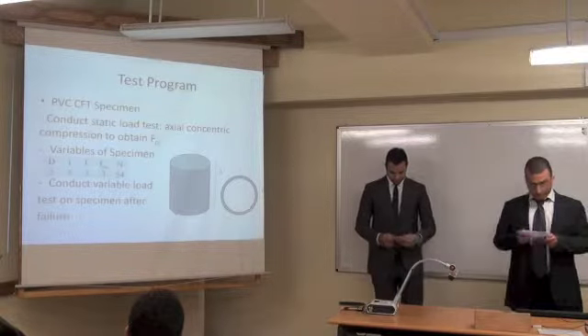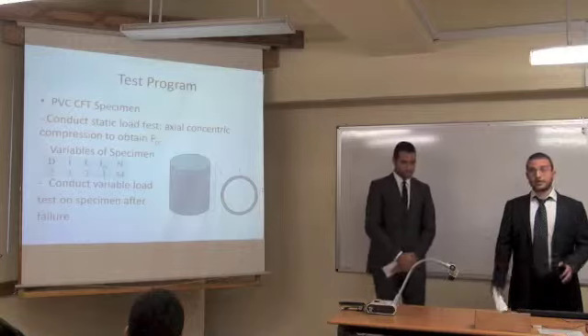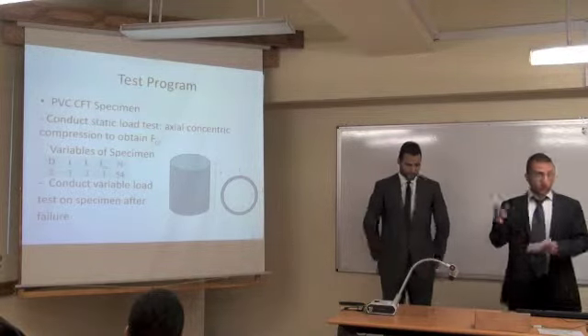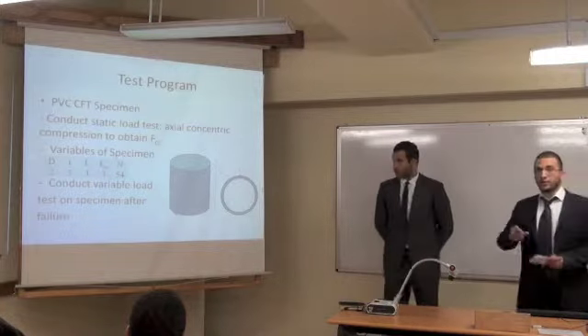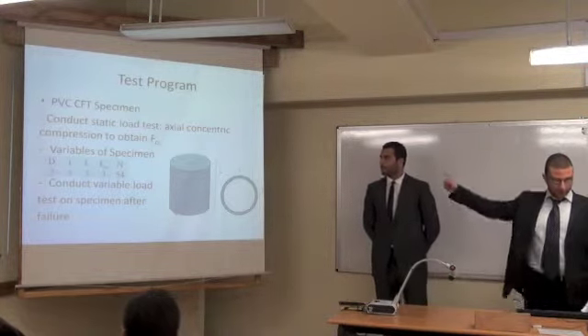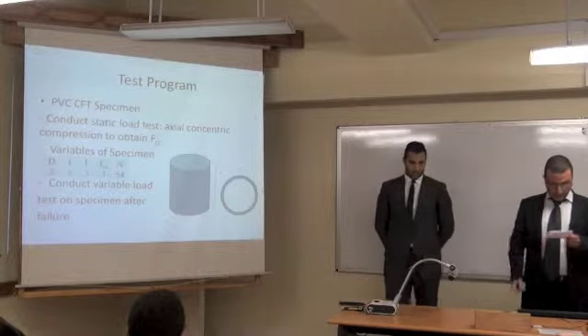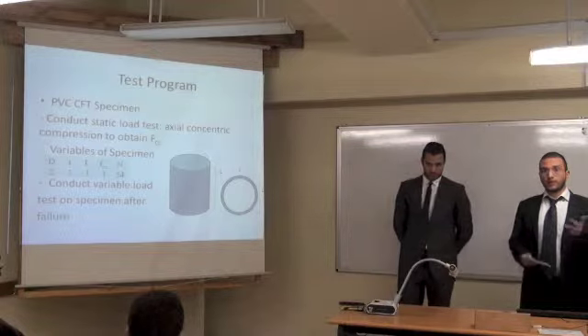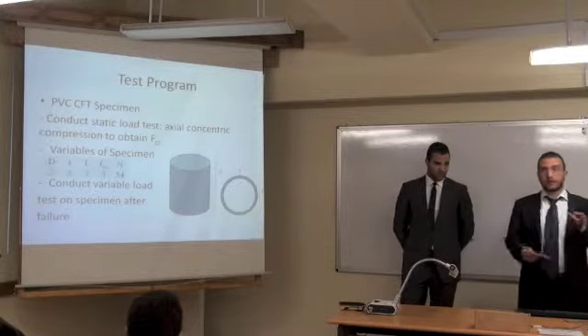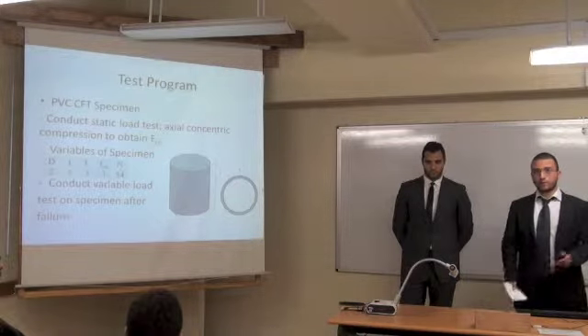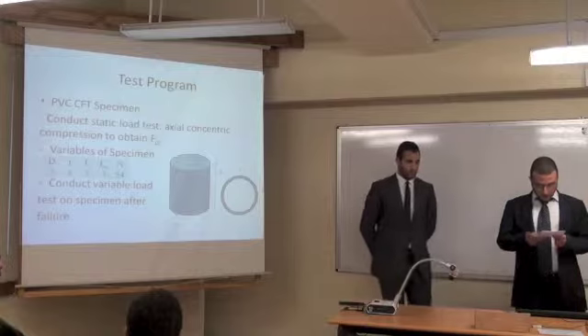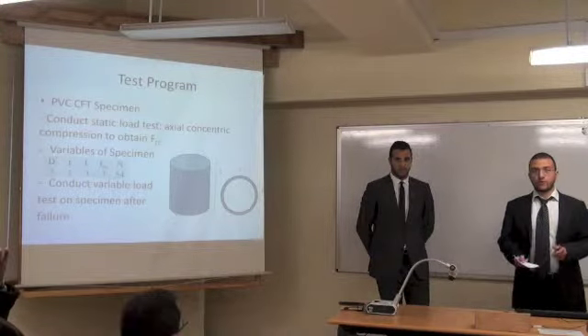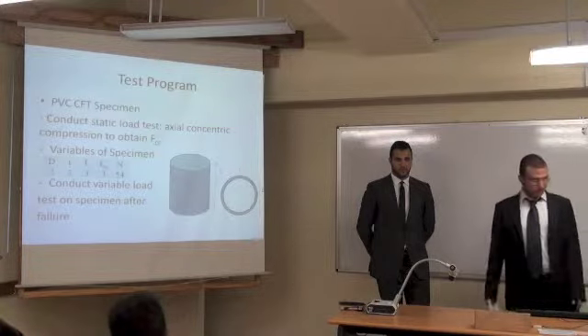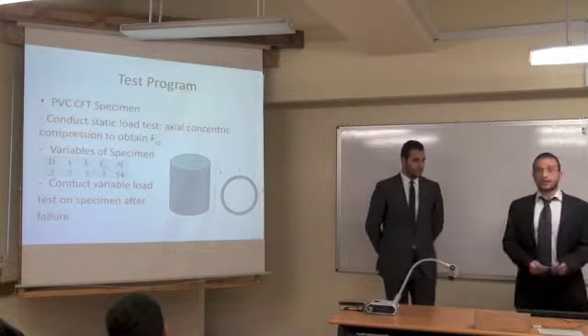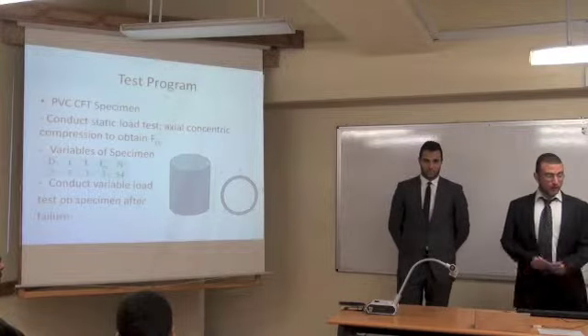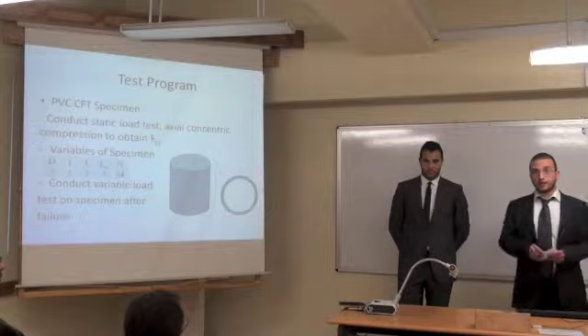The diameter: we're taking two diameters into consideration, 4 inches and 8 inches. The wall thickness, as expressed in the diagram, is the wall thickness of the PVC tube. This is a cross section. We're considering 3 millimeters, 4 millimeters, and 5 millimeters. We're considering 3 different lengths to satisfy the different types of columns: short, medium, long. We're considering 3 different concrete compressive strengths. After we conduct the static loading test, we're considering conducting variable loading tests to test the fatigue of the specimen.